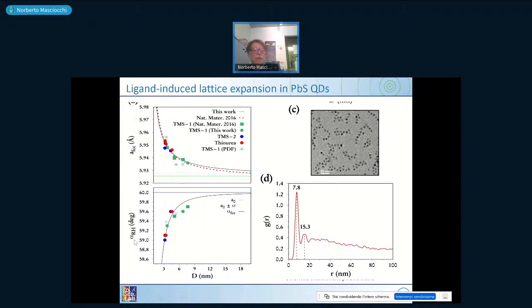You can also plot the alpha rhombohedral, which is far away from 60, and you can see that all these align up with the same trend, and that once you go to 12, 15 or so nanometers, then you lose information and everything goes back to 60 degrees. That means from 12 nanometers up, the system is cubic. The system is not cubic if you have very tiny nanocrystals.